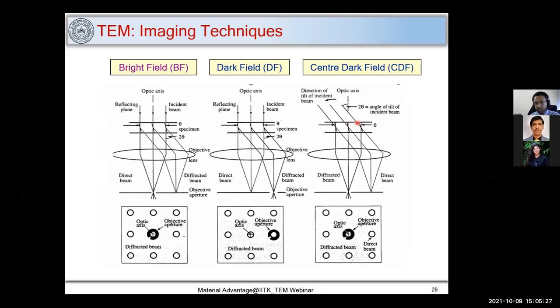Now in this third case, rather than shifting this aperture to a diffracted beam, I'm tilting my beam. So what happens is that the diffracted beam passes through this aperture, and this kind of dark field which we get is called a center dark field. And I recommend that you always go for this kind of center dark field when you want to get bright field or dark field images.